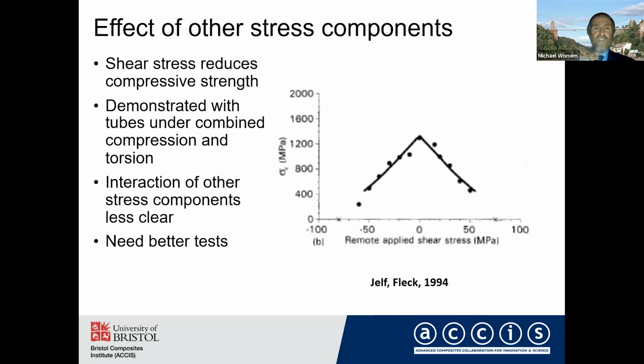Other stress components: I think it's well known that shear stress significantly interacts with compressive strength, and these results from Cambridge from a long time ago, with combined torsion and compression on tubes, show very nicely the approximately linear interaction between compression and shear. But the interaction of other stress components is much less clear. I think we need better tests to try and get to the bottom of that.